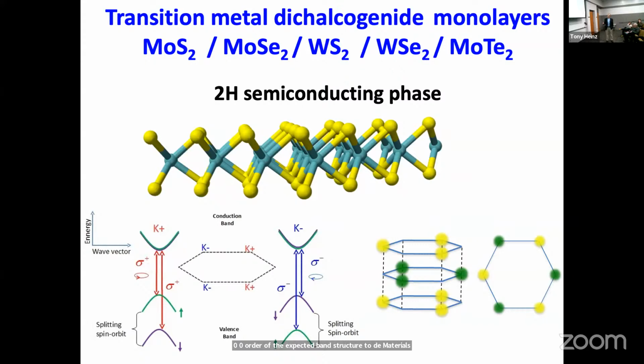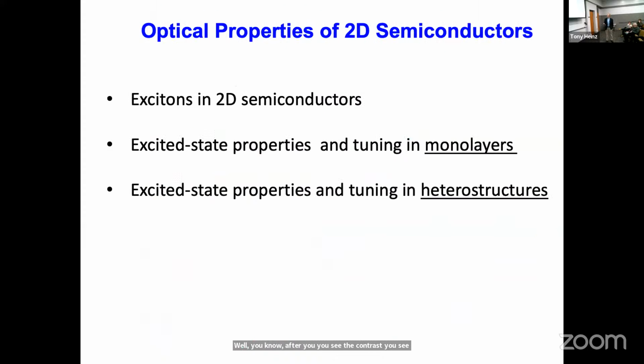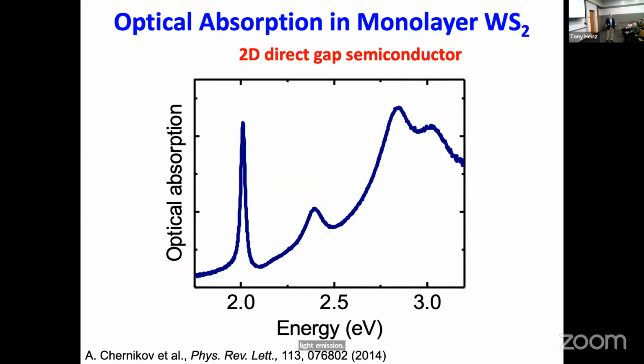Well, after you see the contrast, you see light emission, you want to go to the next step, and that's measuring the absorption spectrum. And here's what we got a fair number of years ago already. You actually see this very, very strong peak at an energy around the band gap, and you see another broader, similar feature at a bit higher energy. This splitting is actually related to the splitting in the valence band from spin orbit interactions that I just mentioned. So a very nice structured spectrum.